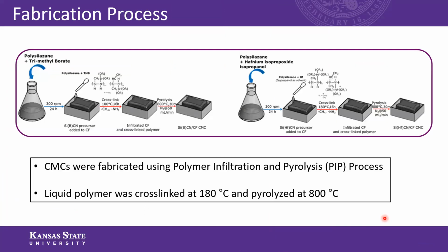And so the fabrication process is as follows. The CMCs were fabricated using polymer infiltration and pyrolysis, or PIP process, which is a well-known process for producing CMCs. And so it starts out with taking the liquid polymer solution, whether that be for SiCN, SiBCN, or SiHfCN. And in an argon atmosphere glove box, the carbon fibers were coated using a pipette.